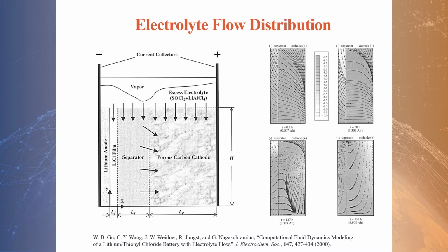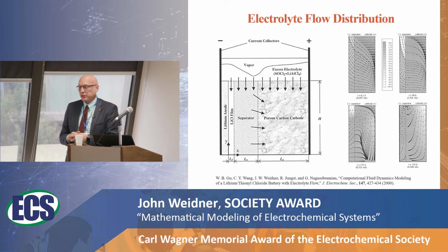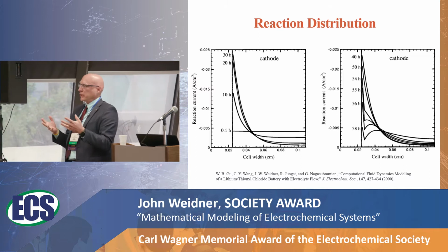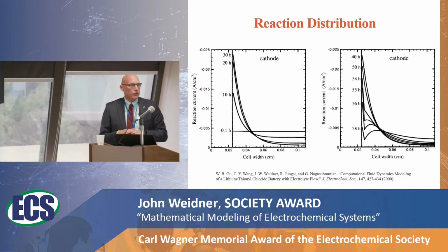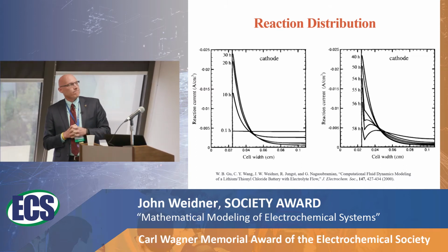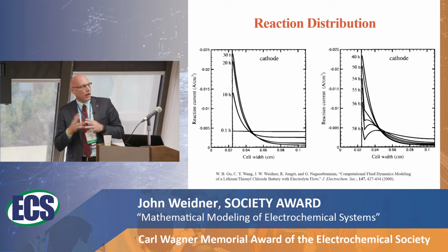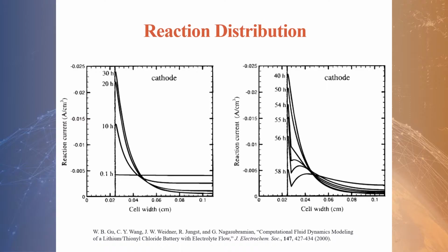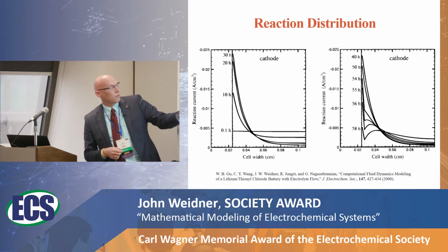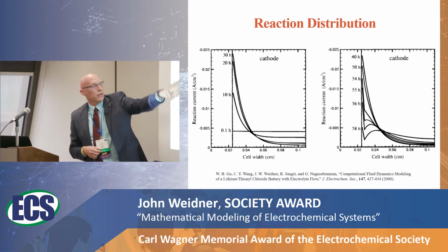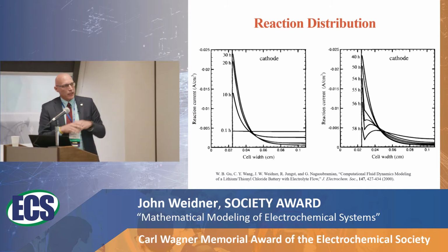So here's an example of some plots of the electrochemistry. Here I'm showing the reaction distribution. Another thing that's very difficult to get experimentally, but again, if you're confident in the physics that you have in the model, you can look at it and understand what's going on. So what we have here is our separator and the beginning of our cathode. So this is our porous region. We have a reaction rate going on inside that cathode, and this is just different moments in time, from 0.1 hour up to 30, and then extending through time.